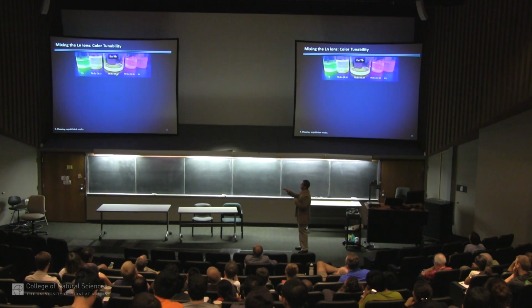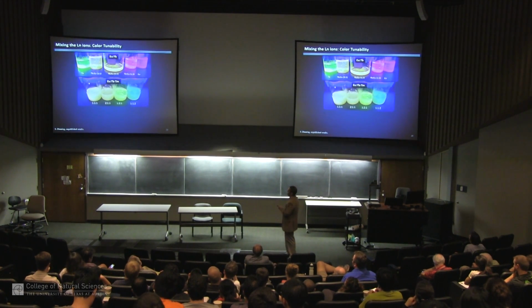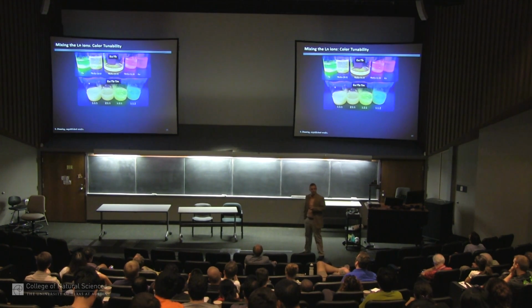So because we can use different lanthanides, the terbium version of the material looks green, the europium looks red. Sam has been able to mix the lanthanides in the materials, and you can see as you do that, you can tune the colors. So if we have one-to-one randomly distributed terbium and europium, you get something that's yellow. If you want a sensor which can give a different color light, you could start to mix in 3 or 4 metals, and we can go from yellow to whiter light or bluer emission.